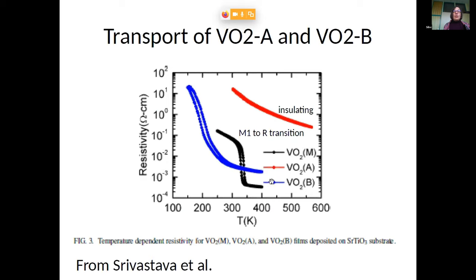insulator to metal transition with a drop of resistivity, again by several orders of magnitude, and under similar conditions, actually even worse or even better than the usual M1 to rutile, monoclinic to rutile transition. So the black curve is the previous monoclinic to rutile transition, while what I label B phase here is both the high resistance, high resistivity, and low resistivity state. And we will refer to them in the following as high T, HT, and low T, LT B phases.